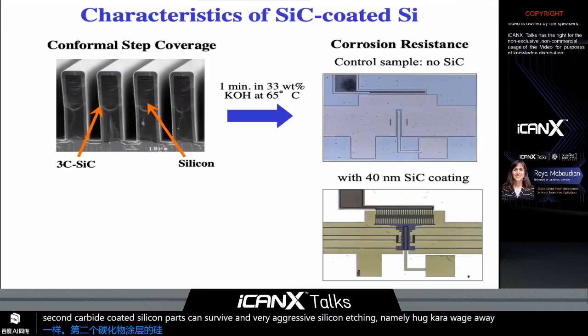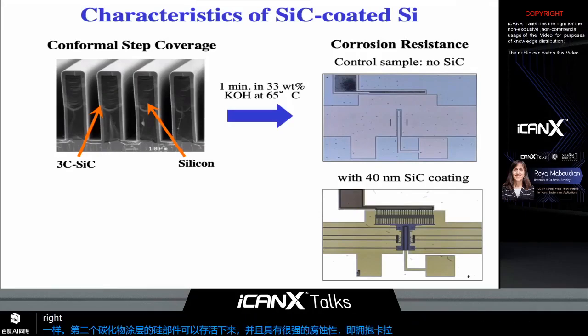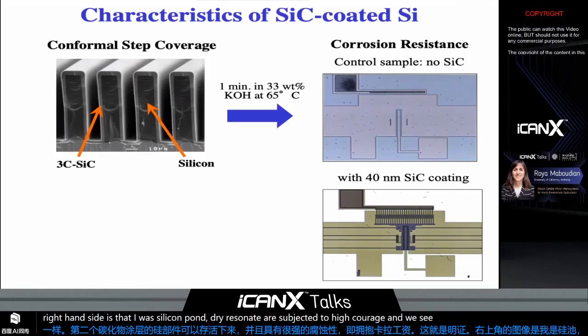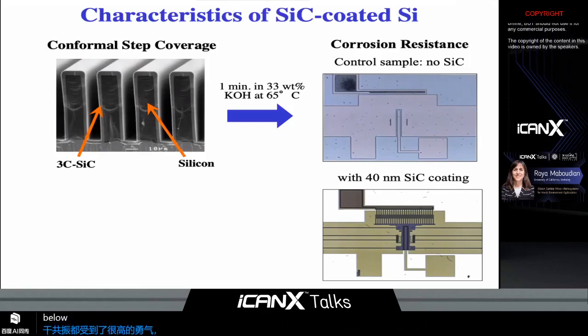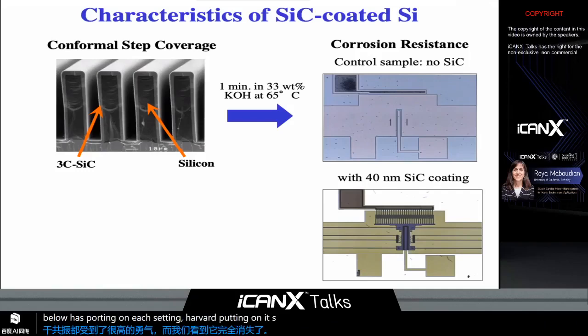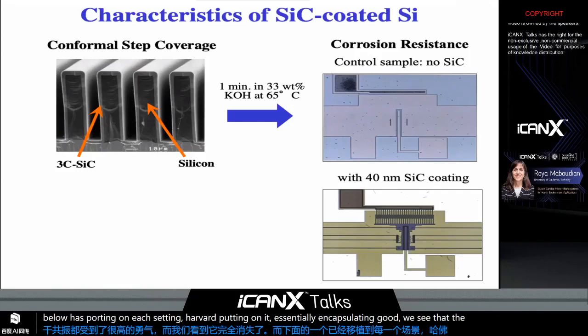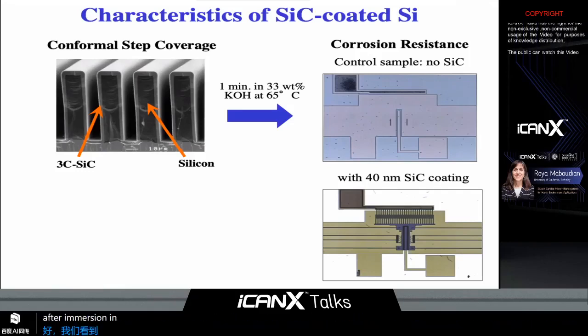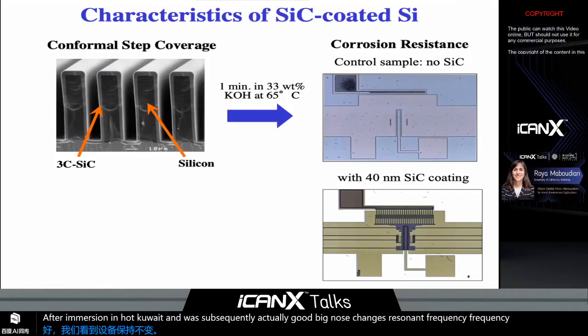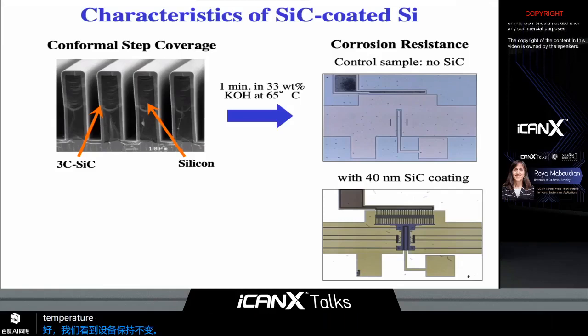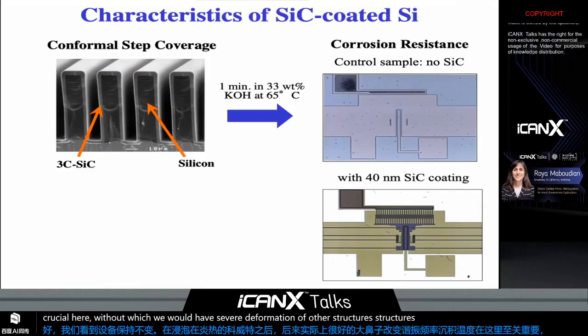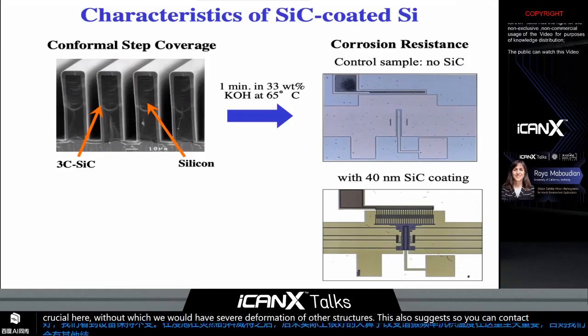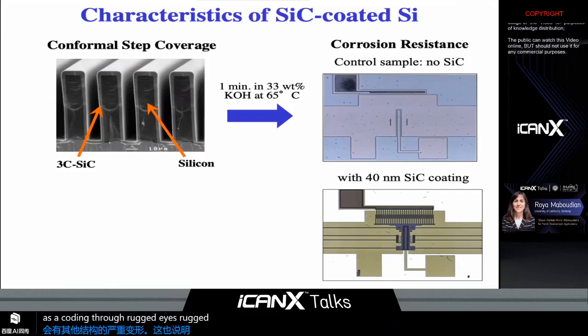The image on the upper right-hand side is that of a silicon comb drive resonator subjected to hot KOH, and we see it is completely gone, while the one below has 40 nanometer silicon carbide coating on it, essentially encapsulating it. We see that the device remains unchanged after immersion in hot KOH and was subsequently actuated with no changes in resonant frequency. Low deposition temperature is crucial here, without which we would have severe deformation of our structures. This also suggests silicon carbide application as a coating to ruggedize silicon microsystems.